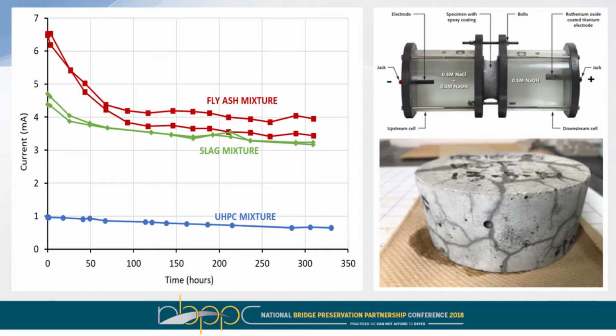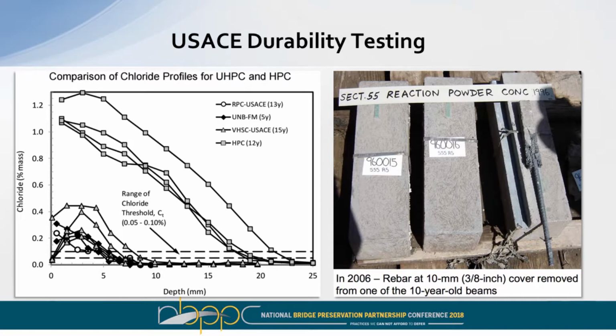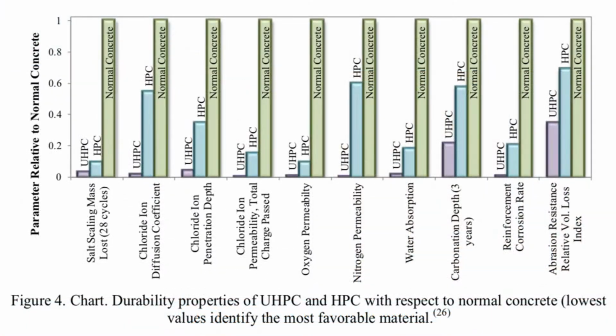And then, of course, we also look at cracked properties. The photo on the bottom left is a section that has been cracked intentionally, and you can see the fine micro cracking nature of this material, really all held together by these fibers. Impermeability is just one parameter. We have good abrasion resistance, we have good freeze-thaw resistance. You name it, in comparison to high performance or conventional concretes, we're much lower than these other mix designs. And this gives you a side-by-side comparison of what these might look like.